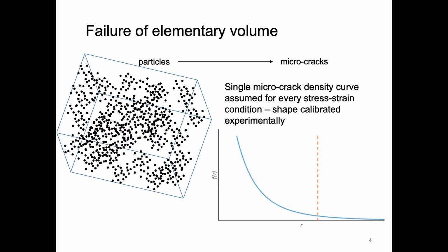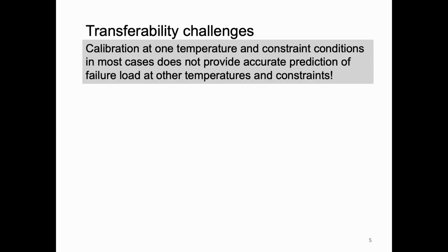But when you calibrate at one temperature and one constraint condition, and you want to move to another to predict probability of failure at another temperature, another constraint condition, or irradiated condition, you fail. So essentially, this is the distribution of microcrack density, and there is a critical microcrack size, and if there is a critical microcrack in your structure, then it can propagate. So that is the challenge, and it has been the challenge all the time, although there have been a lot of trials to fix the problem. Eventually, when you calibrate at one temperature and constraint condition, you cannot, in most cases, provide accurate prediction at another temperature or constraint condition or irradiation condition.